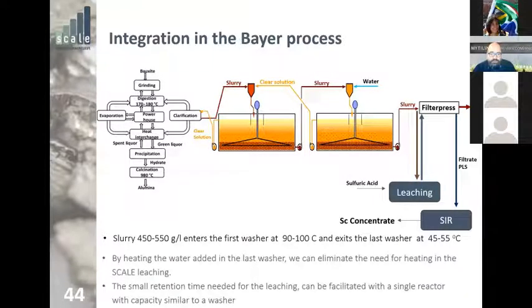And we can imagine that we can optimize this process greatly if, instead of adding cold water, we added just hot water. There is a lot of heat exchange capability inside the Bayer process, so we could eliminate a significant amount of energy for this process. And also the small retention time, we're discussing about an hour of leaching, means that you don't need huge reactors. You just need to have another washer next to your last washer, basically.